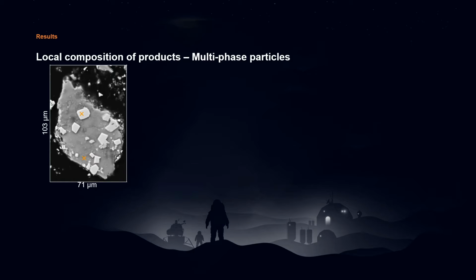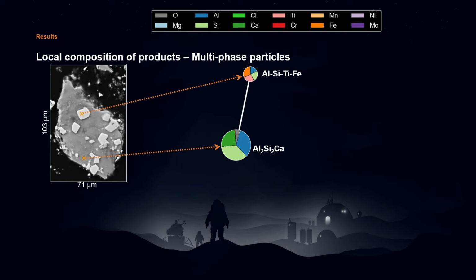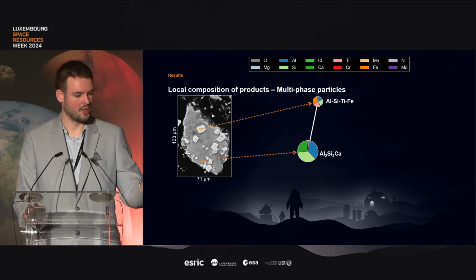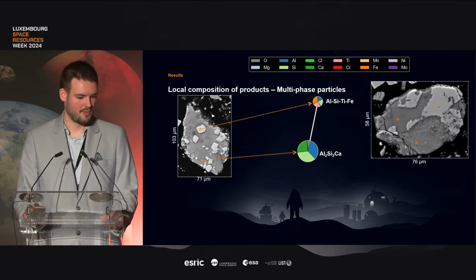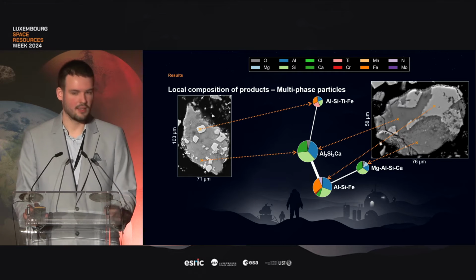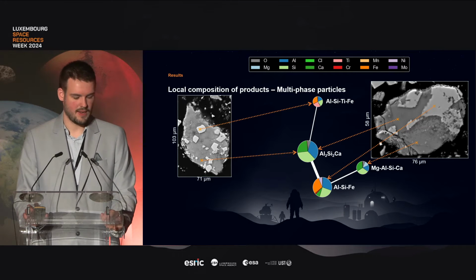If we look at the morphology, we can see that a lot of those phases actually occur simultaneously in one particle. So the example of this particle here, we can see two points we analyzed. Looking at the composition, we have an aluminium silicon calcium matrix with some inclusions of this titanium-rich compound we identified before. I'm going to plot those here now, and we can do this for a number of particles. So we connect them because they're in the same particle. Next particle I'm taking here will do the same thing, and I guess you can see where this is going. So here we have, again, this aluminium silicon calcium compound, this time combined with aluminium silicon iron, and also with a magnesium version of the initial compound.